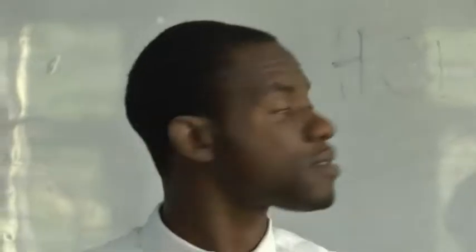These are my outlines. Ceramic water filter. A ceramic filter is an inexpensive and constructible type of water filter that relies on the pore size of the ceramic material to filter dirt, turbidity, and color out of water. It is basically a mixture of clay, sawdust, and water molded and fired in a furnace. The sawdust material burns out at a temperature of about 400 to 500 degrees Celsius, creating pores.